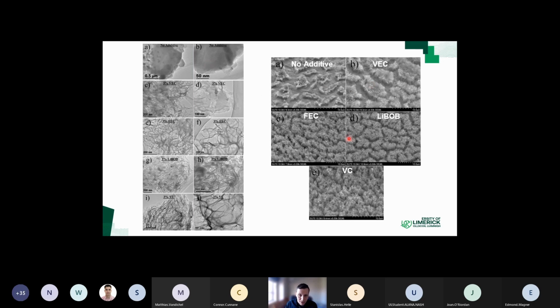So if you looked at SEM images of these, you can see clearly that with the no additive, when you wash it, you lose a lot of the material. So it's not well contacted to the current collector, whereas with VC it is, and actually for the 3 best performing ones in terms of capacity retention it is. So even after washing, you can see the material is still very well adhered to the current collector, whereas the no additive one, you can see a lot of bare patches there. The reason for that is because, again, the no additive one is not forming that stable morphology. It's forming this amorphous mass, which is not well contacted to the current collector.